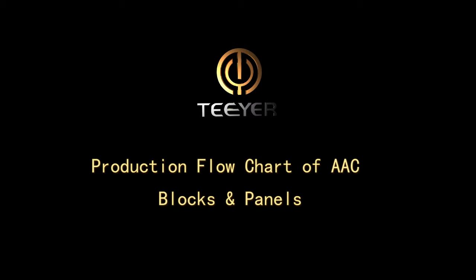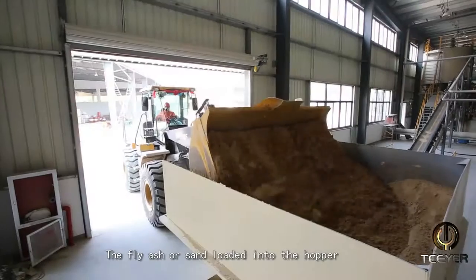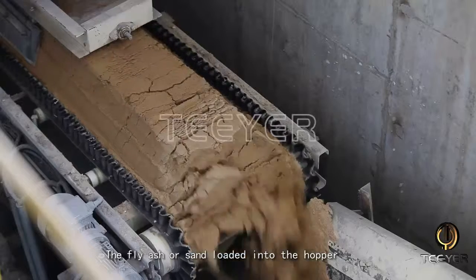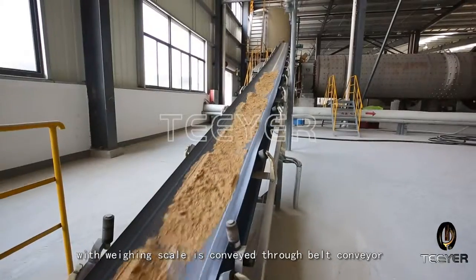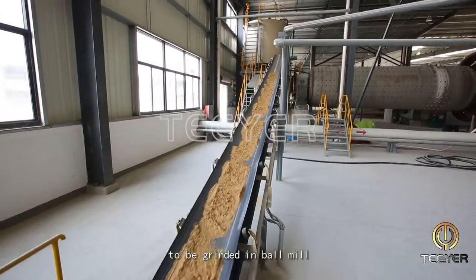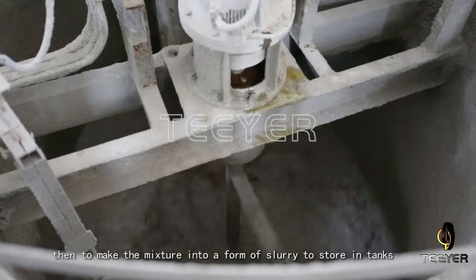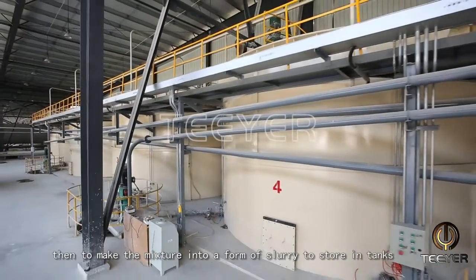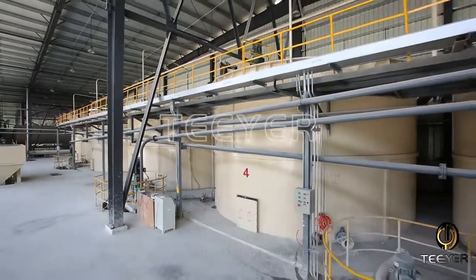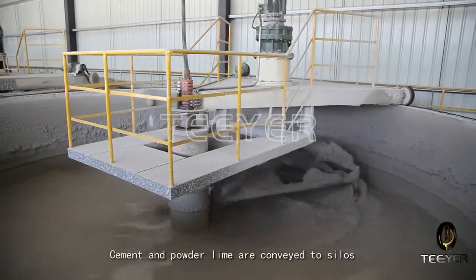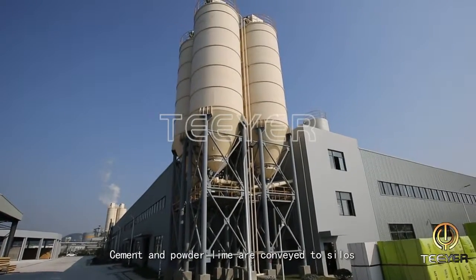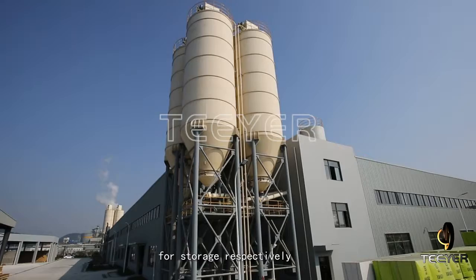Production flowchart of AAC blocks and panels. The fly ash or sand loaded into the hopper with weighing scale is conveyed through belt conveyor to be ground in ball mill, then made into a form of slurry to store in tanks. Cement and powder lime are conveyed to silos for storage respectively.